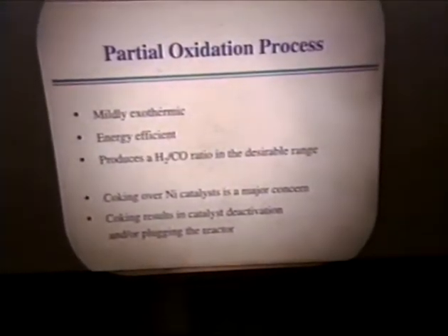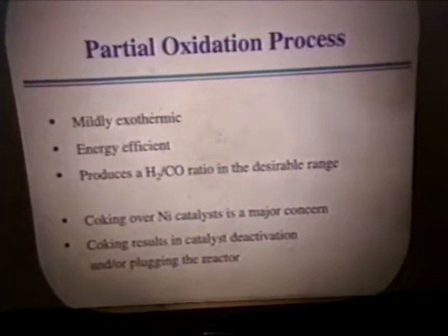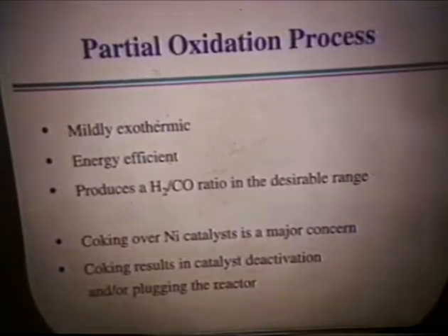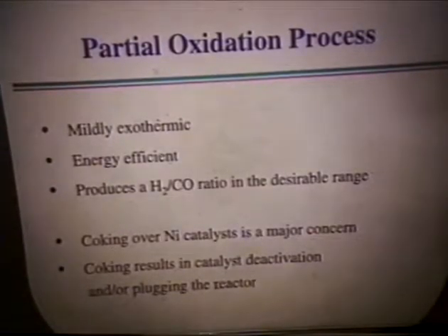If you do it selectively, it can be a mildly exothermic reaction. Therefore, it's energy efficient, and you produce your hydrogen to CO ratio in a preferred quantity of 2 to 1. Traditionally, nickel catalysts haven't been very successful because of their coking problems. But in this paper, you'll see some work where we've made some improvements there. Once you have coking, of course, you're going to have deactivation and the catalyst plugging the reactor. So that can be a major problem.